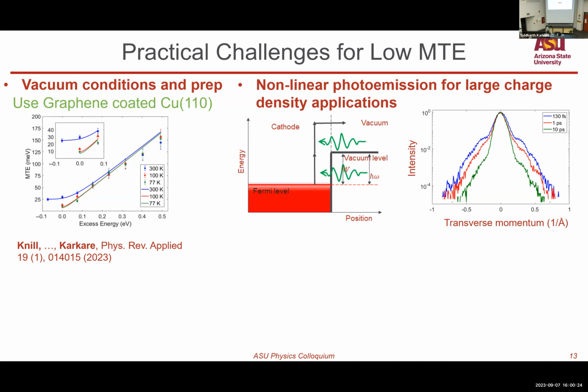If you see, these photoemission peaks are a couple of orders of magnitude smaller than the linear photoemission peaks. But turns out, since they come out at a way higher energy, these linear electrons are going to come out with milli-electron volt scale energies. These non-linear electrons, even with 2-photon emission, are going to come out at 4,000 milli-electron volt scale energies. So even if there's very few of them, they destroy your mean transverse energy.